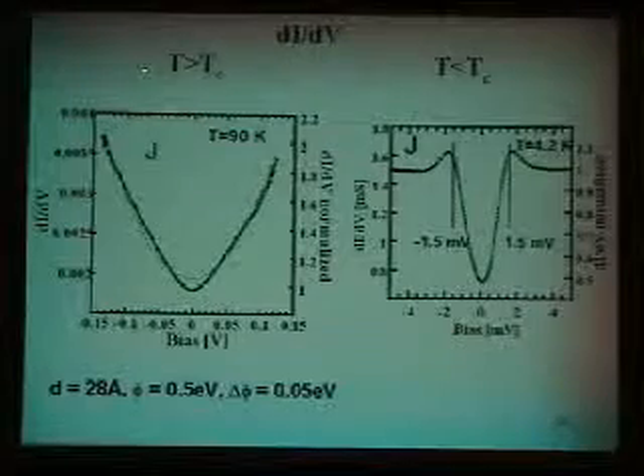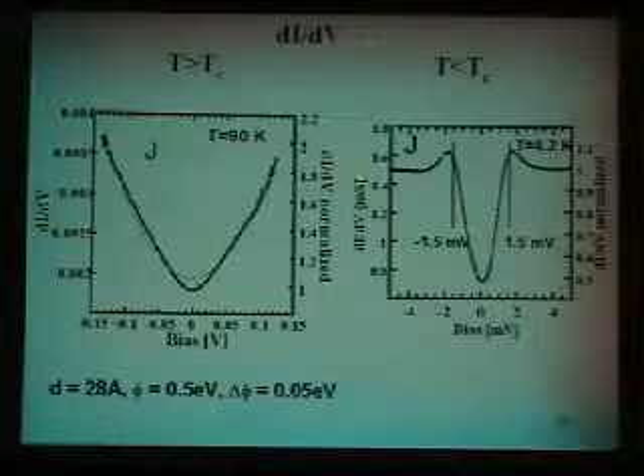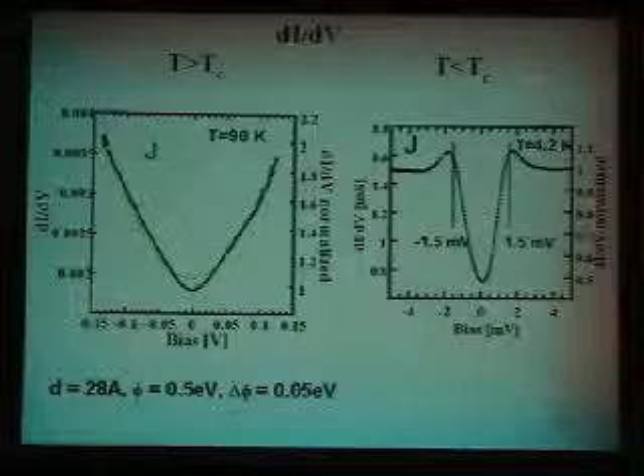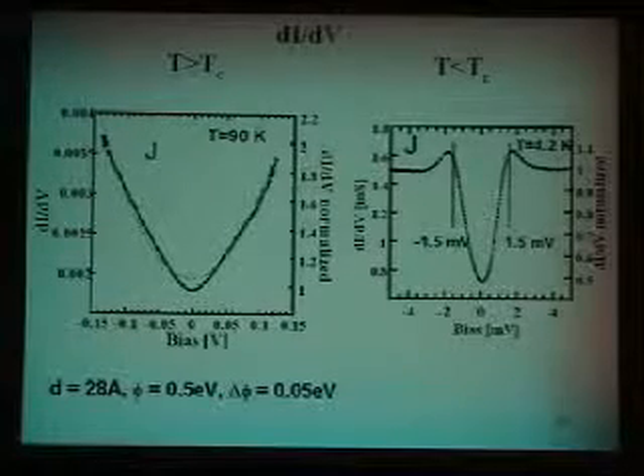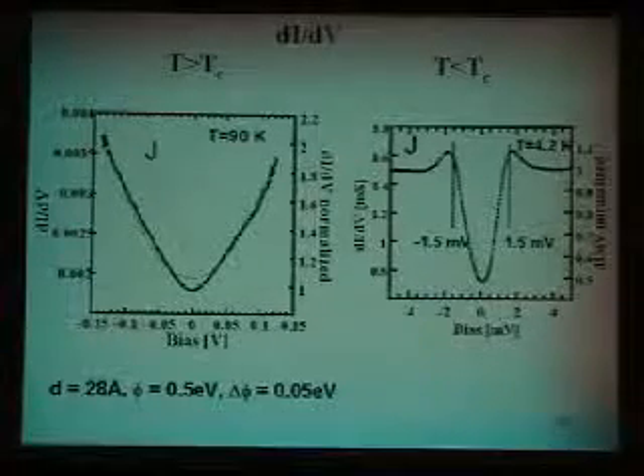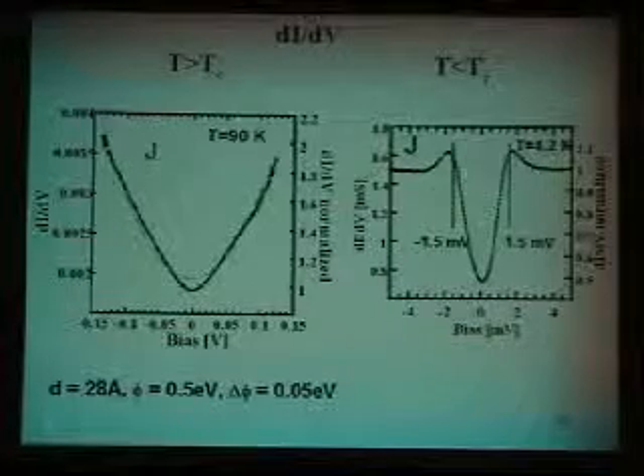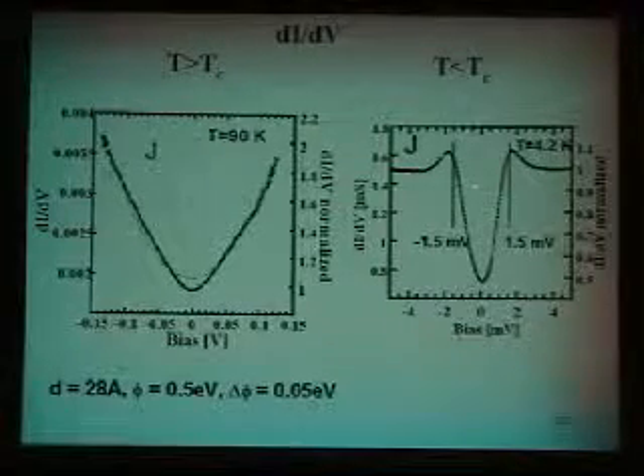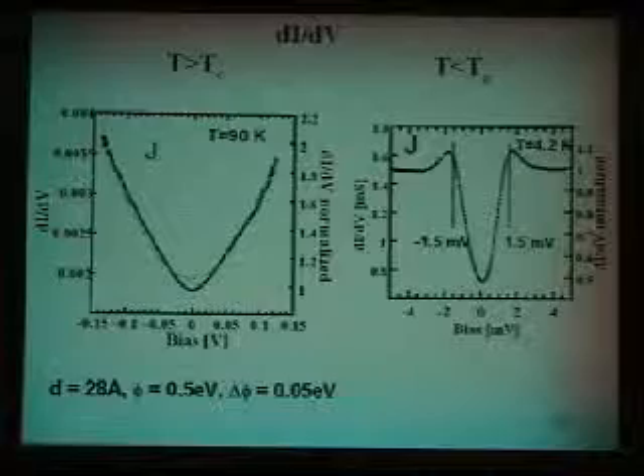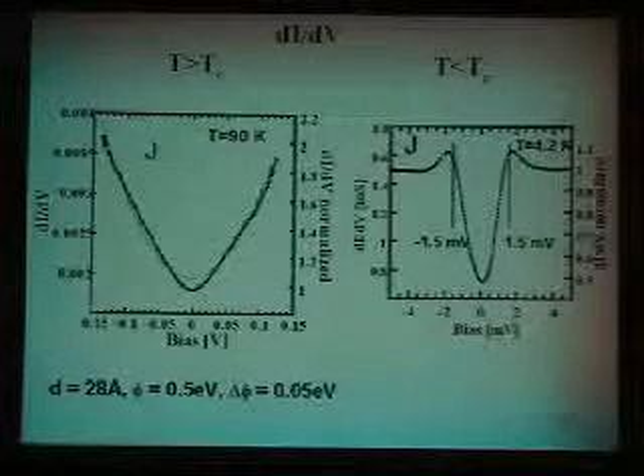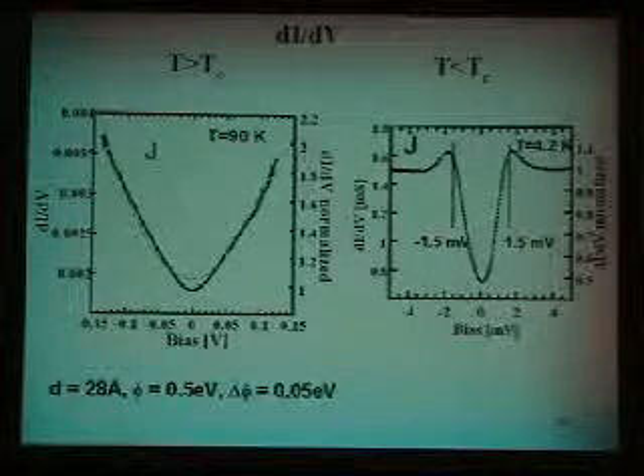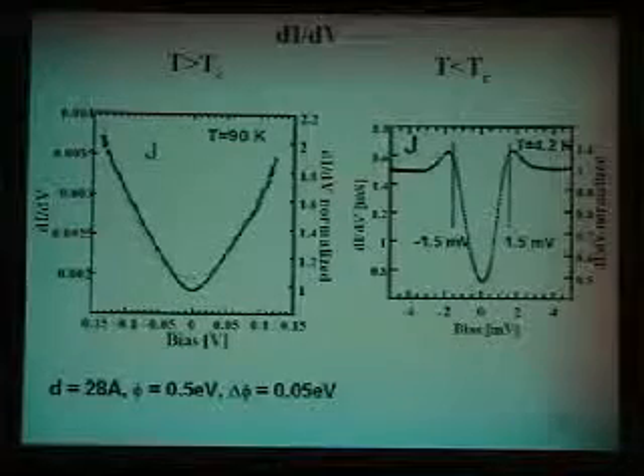If you cool this one sample down to low temperatures, the dI/dV now looks like a classical tunneling curve for a good superconductor-insulator-normal tunnel junction. That's how this green curve is. It gives you the right gap, and everything is right. So this is a good junction. Notice that I'm plotting here the IDV.